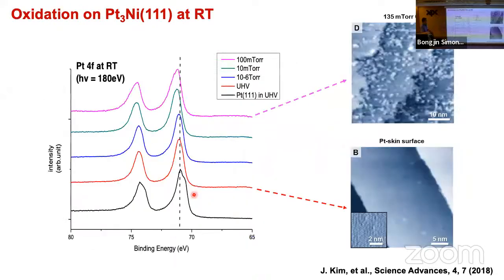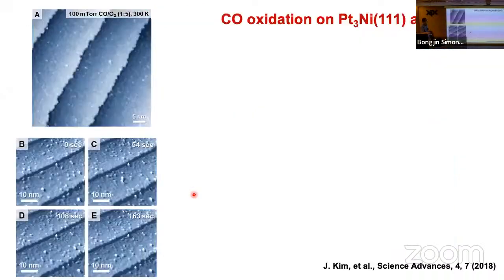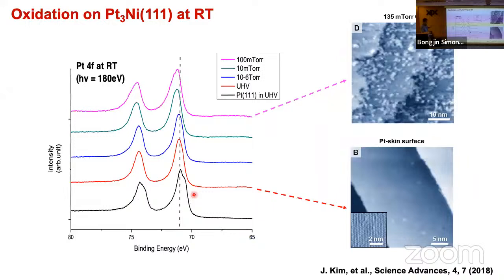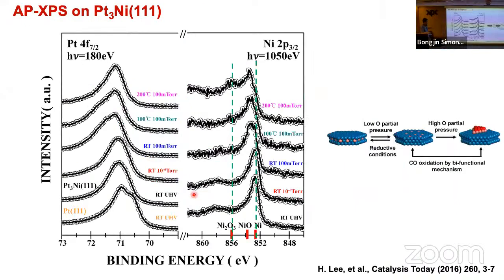So when we compared these two, we were able to find the condition that at a clean platinum skin surface, you see this fine metallic state. But when you introduce the oxygen, not a lot, at room temperature, not even high temperature, room temperature, about 100 millitorr, you start to see this roughening. And we now know that this clustering is actually not the platinum, it's actually the nickel that comes up and gets oxidized. So here is, by the way, this nickel, and then we thought, okay, then what is the chemical state of this? Well, this is nickel oxide that we just see here.